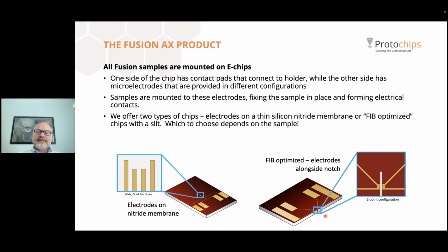The electrodes are isolated from the substrate by thin dielectric layers. So 2 examples of these styles are shown here. On the left, these are electrodes on a membrane, spaced microns apart. On the right, electrodes near a notch, again, microns apart.